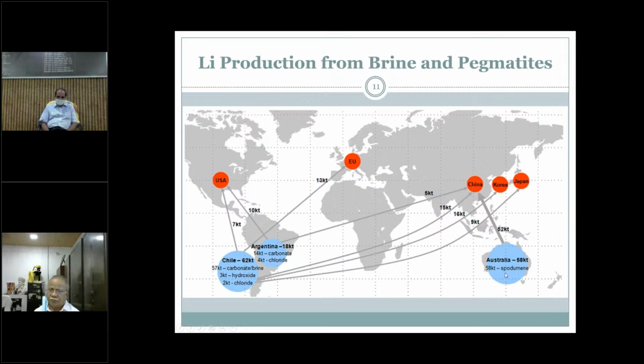You can see from Australia about 58,000 tons were produced in the year 2019, which is mainly spodumene concentrate. But when it comes to Argentina, it is the brine, and it is in the form of lithium carbonate and chlorides. And with respect to Chile, about 62,000 tons were produced, mainly in the form of lithium carbonate, hydroxide and chloride.